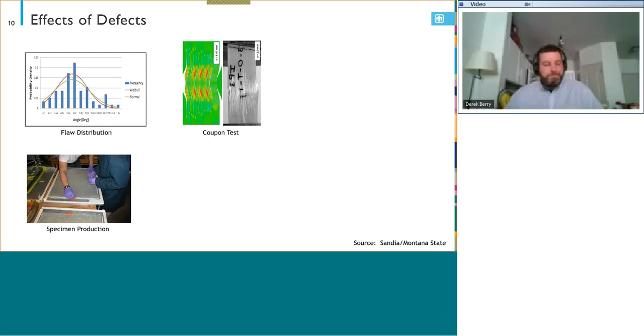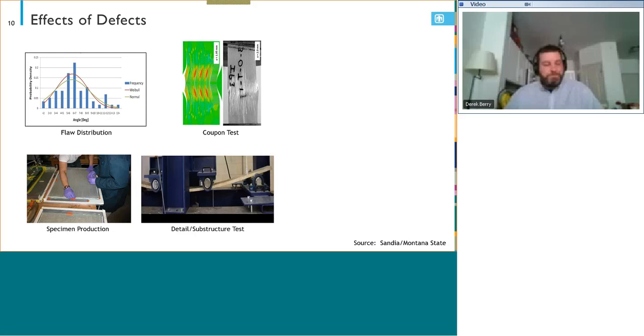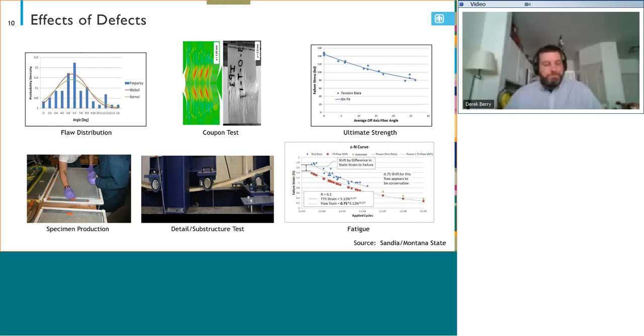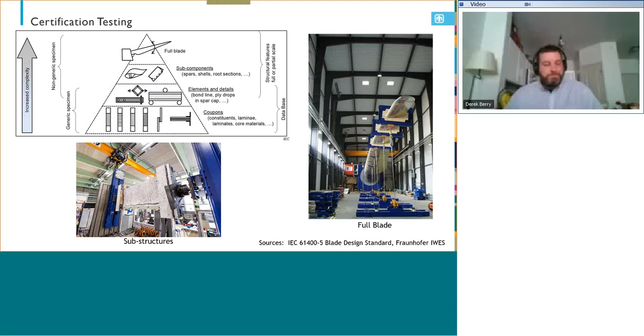Then from there, you would make some specimens that have those flaws. That's not a trivial thing to do, but it can be done. Then you make coupons from those plates that have whatever type of flaw you want to examine, in this case an in-plane wave. Do coupon tests, and in some cases you may need to do detail or substructure tests at a little bit higher level. Then do many of these tests and understand the effect. In this case I've shown both ultimate strength and fatigue. In the first plot is strength as a function of the wave angle, and the second is the effect on fatigue for a flaw. So you can see those differences, and in this case you'd be able to quantify that, and since you've quantified it, use a lower safety factor.